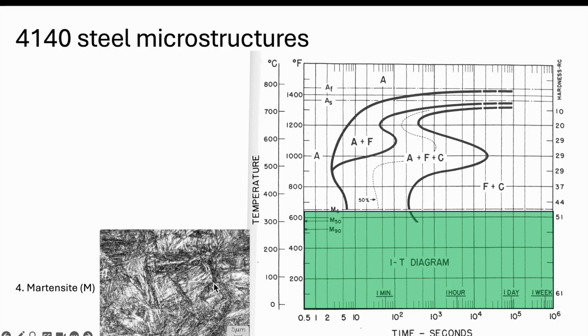And it can also look a lot like bainite, which I'll talk about when we look at more specific microstructures. One last thing I'll point out here. You might notice that it says martensite start, martensite 50%, martensite 90%. So martensite doesn't always consume the entire microstructure. It can be about 90% or so, with the rest being austenite. So austenite can actually remain in the structure. A lot of times if you see lighter regions, those are potentially austenite regions of the microstructure.